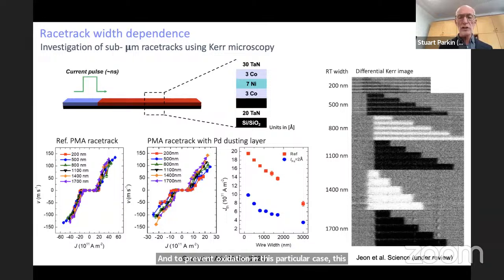And we explore the motion by, as you can see on the right-hand side, using Kerr microscopy, which is, of course, an imaging technique where we look at the reflection of polarized light, and it's deflected to the left or to the right in reflection, whether we have up or down magnetization. And this is shown then in a sequence. Let's say at the bottom, you can see 1700 nanometer wide racetracks, and we're showing an image of a single domain wall where the magnetization is black is up and gray is down. And then we apply a current pulse, and the domain wall moves along the racetrack. We take another image, and by taking a series of images in the Kerr microscope after applying one or more current pulses, the domain walls move, and we can determine their velocity.